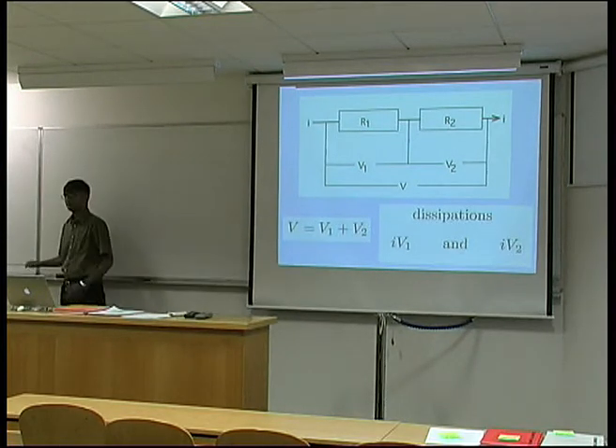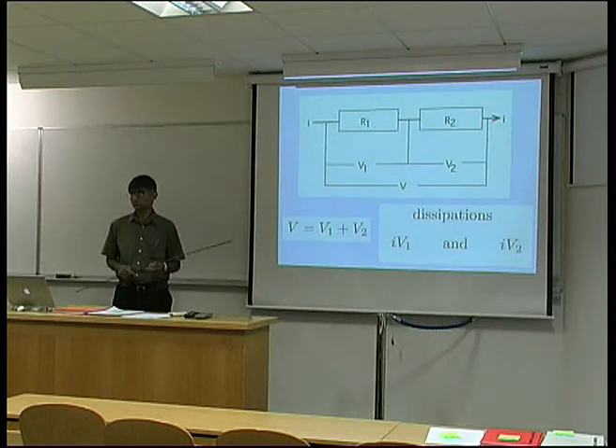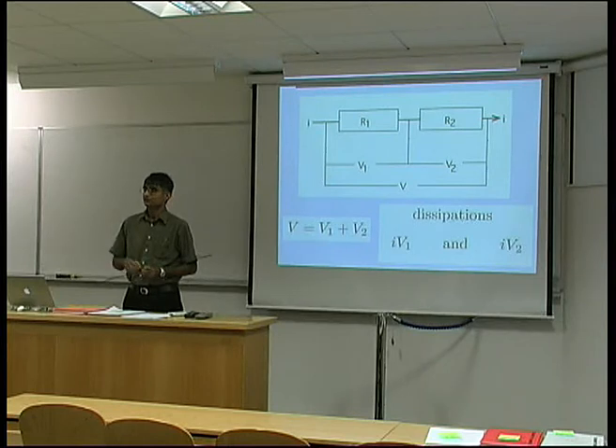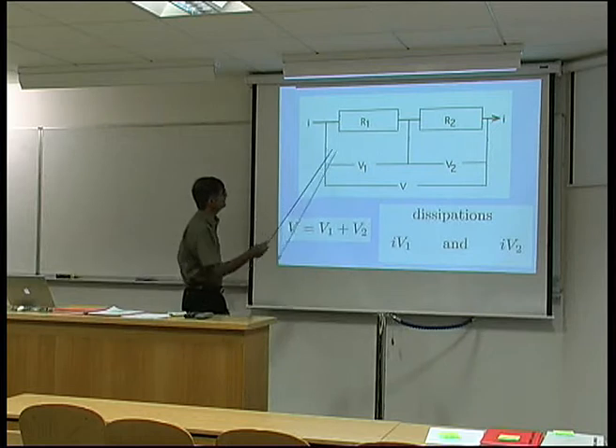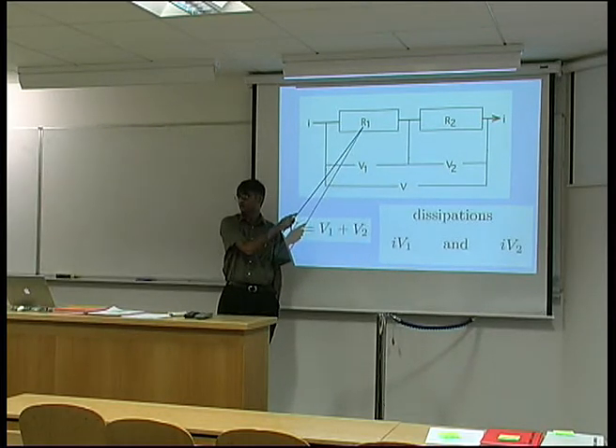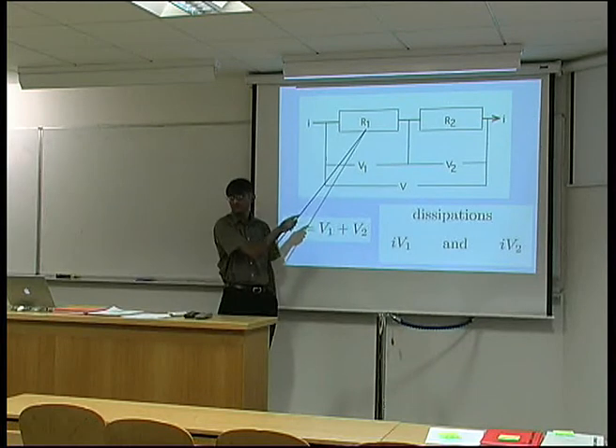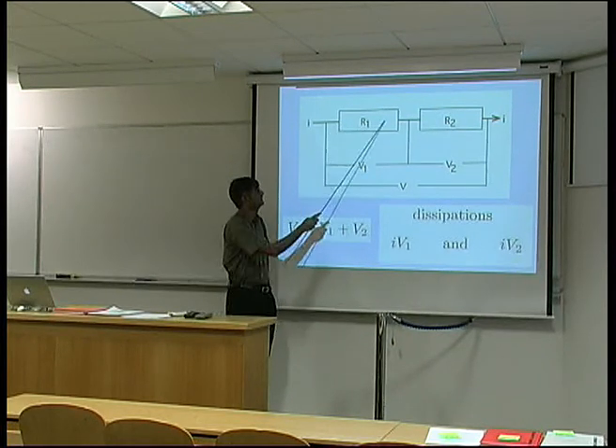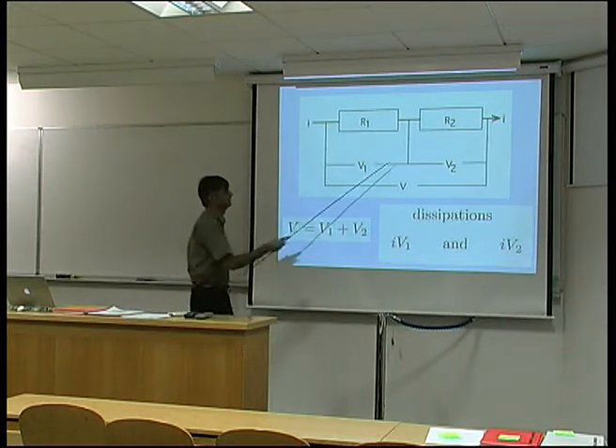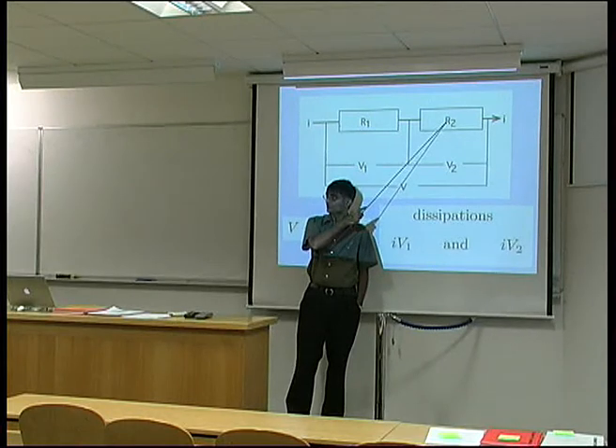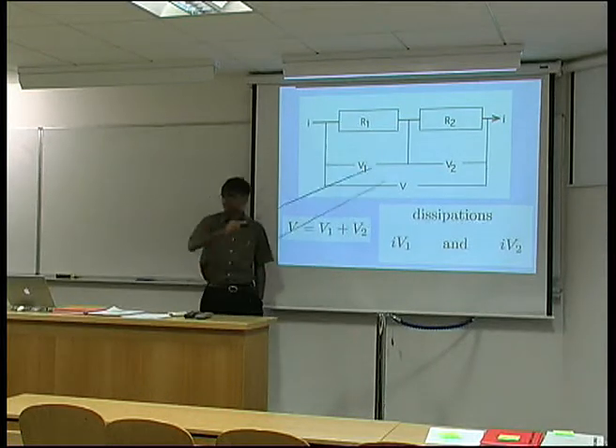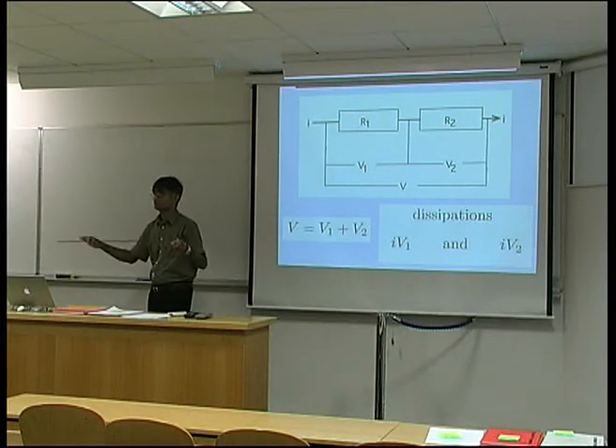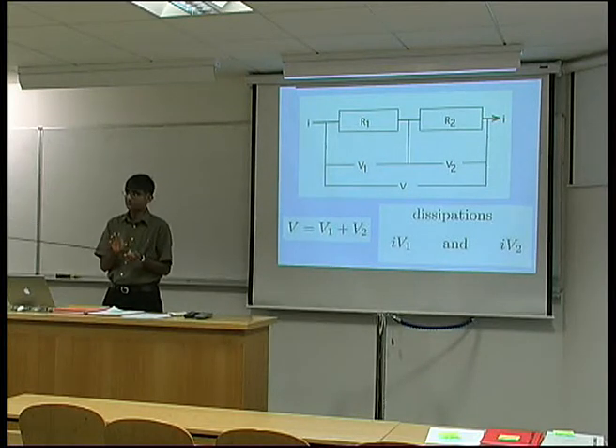In general there might be a whole series of processes which control the rate of a reaction, and each of these processes will dissipate energy. I've got an electrical analogy here — this could be the process which describes the diffusion of solute ahead of the interface, represented by a certain value of an electrical resistor. The transfer of atoms across the boundary may be dissipating some of the free energy, represented by another resistor, and I could carry that series of resistors on for each of the different processes which limit the growth of the particle.